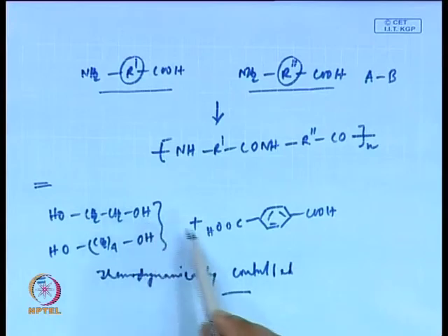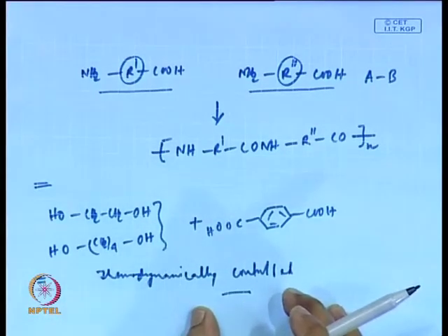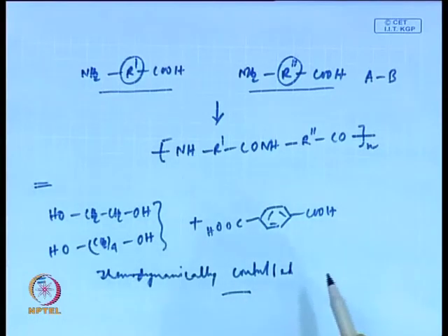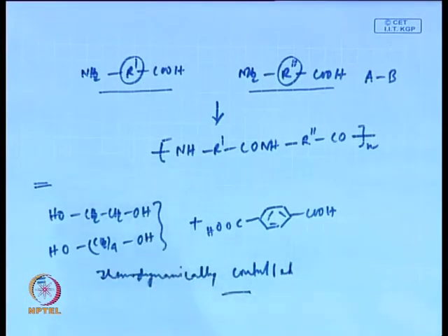Okay. You understand why? Because this reaction, when it is happening, is a slow reaction. So, during the reaction time, the byproducts also take part in the reverse reaction, and the intermediate chains are also reacting with each other by ester exchange, and by doing so they are always reshuffling between themselves. At the end, you always have a completely random copolymer.